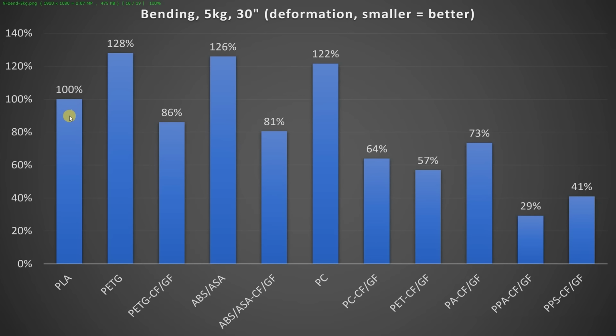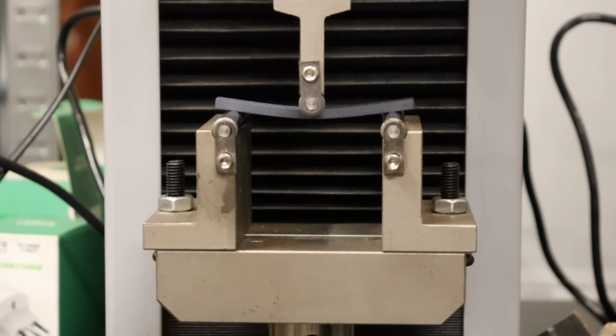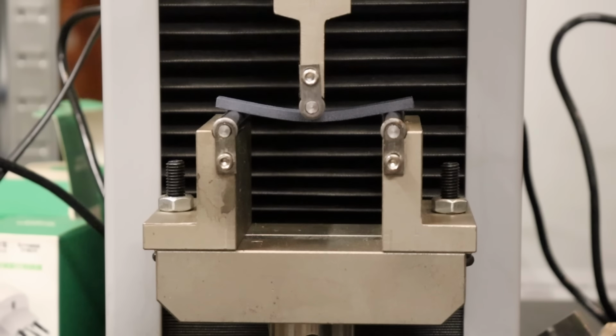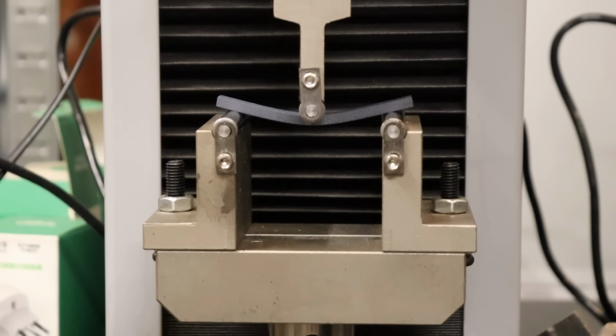And there are several conclusions. First is that from all non-fiber-reinforced filaments, the PLA is the strongest. Another conclusion, that the fibers help in every case, no exceptions. And from all filaments, the two strongest are the PPS-CF and of course PPA-CF, with very minimal deformation during this test, even under 5 kg.